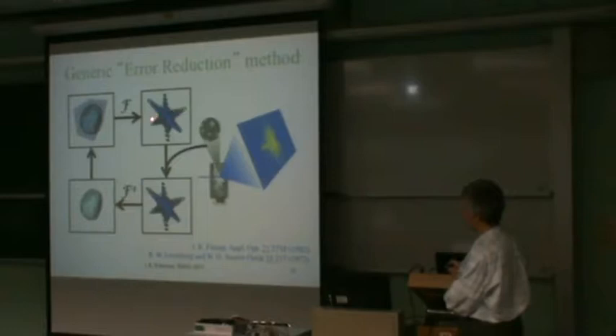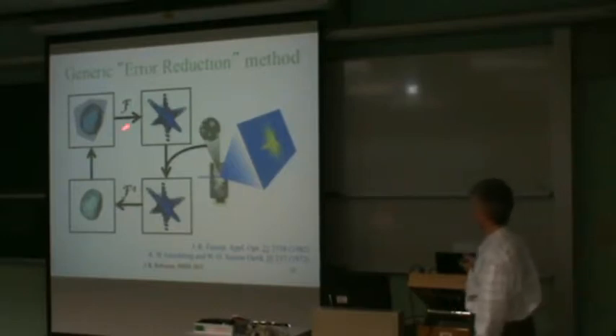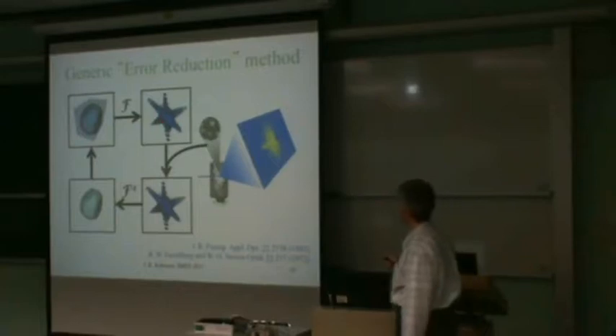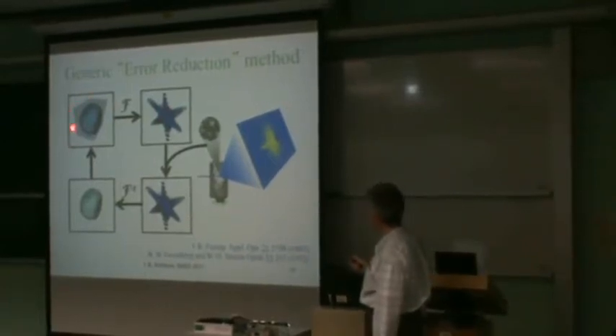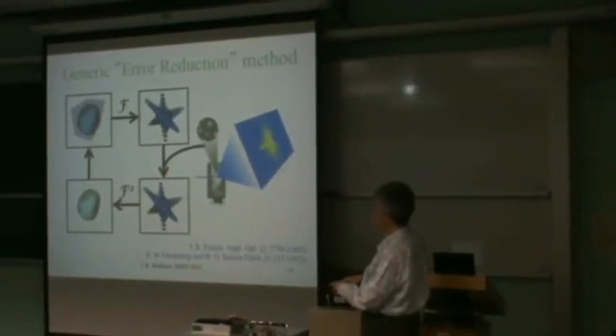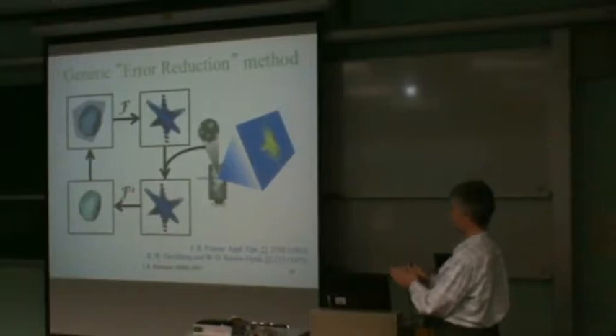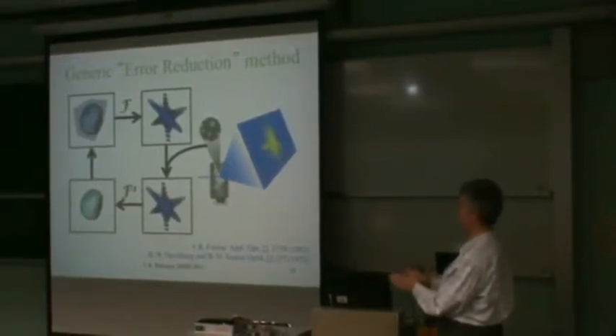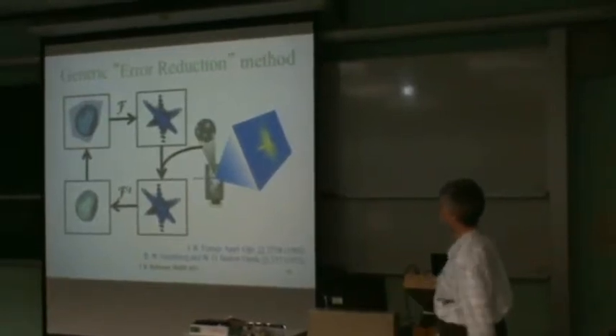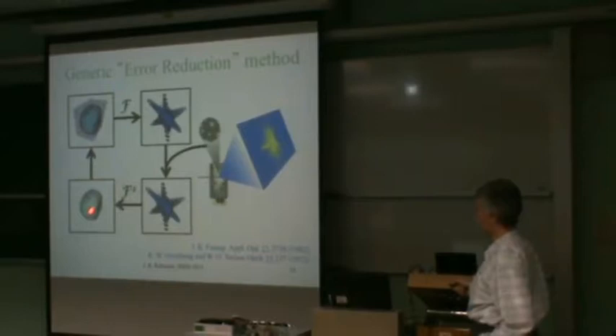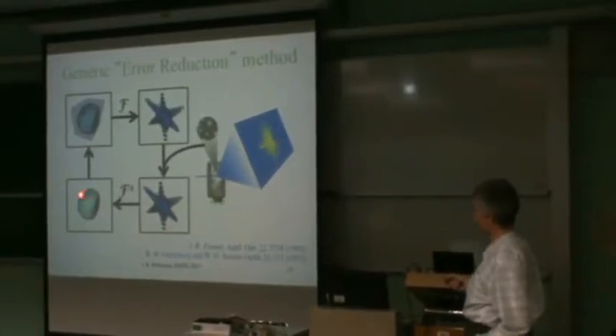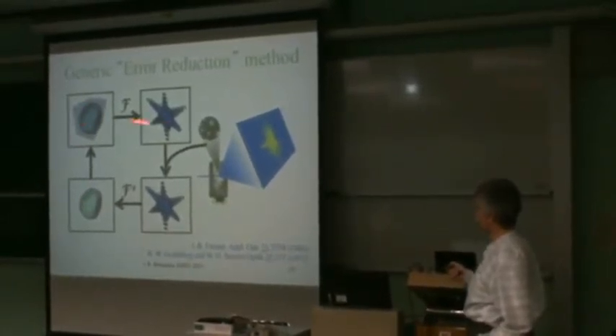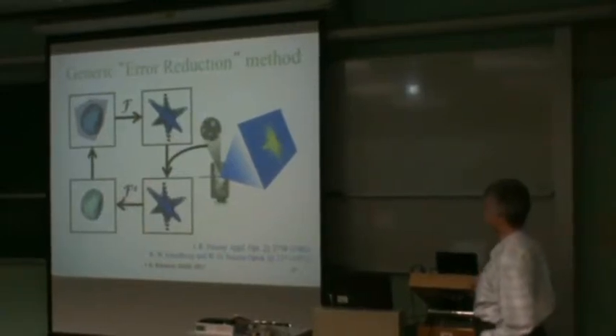And that's seen by the fact that you have more than two pixels per fringe. So you're above the Shannon frequency of the information that's in this diffraction pattern. That means that you can use as a constraint in real space what's called a support, which is a mathematical box drawn around the sample, and you just say that the whole sample has to live inside that box, so you can use it as an algorithm step by just deleting everything outside it. So the real space part of the algorithm is to take the iterate that you would have of the image of the three-dimensional particle, cut it off with this support, come back to reciprocal space, you get a diffraction pattern which is only correct to the extent that the object you started with is correct.